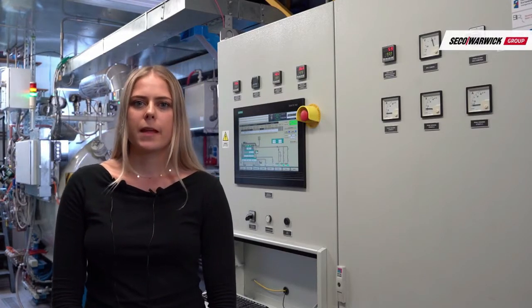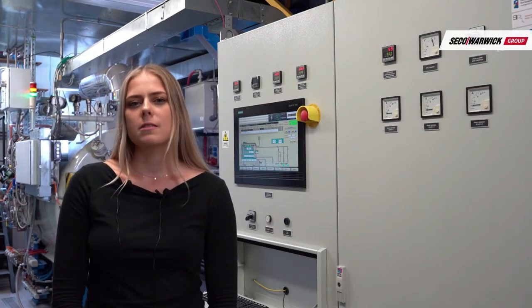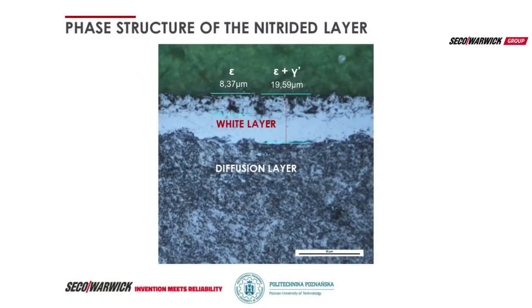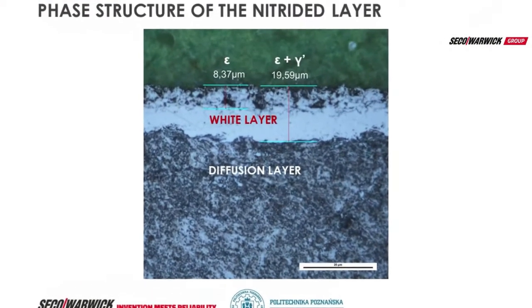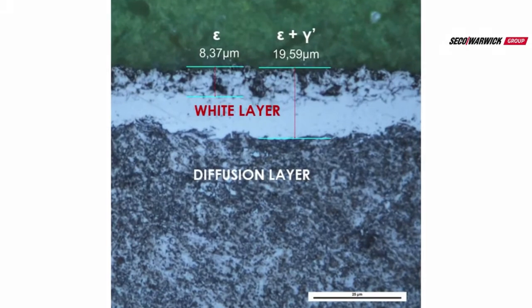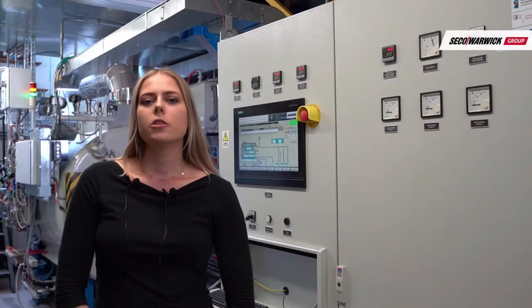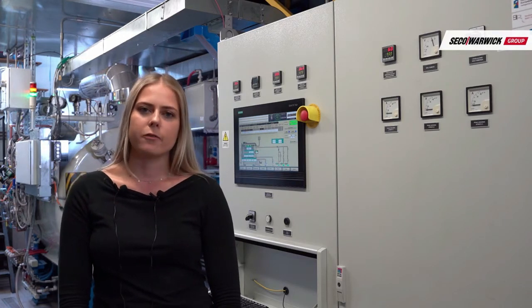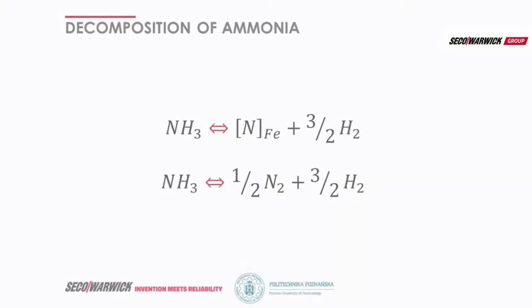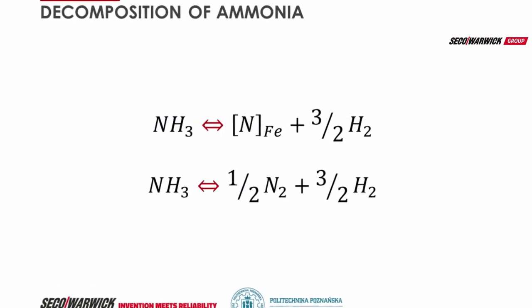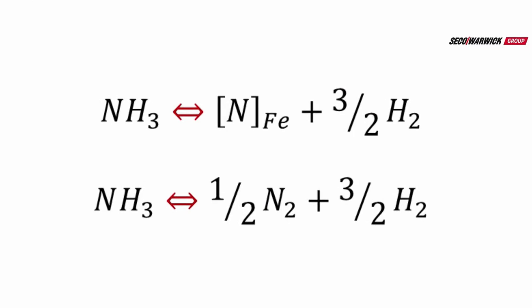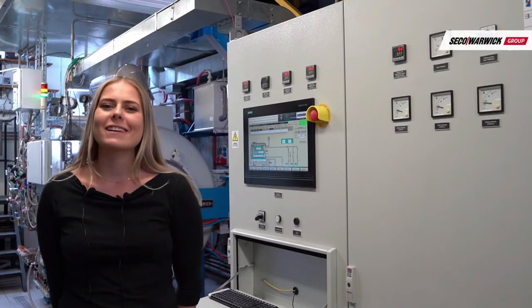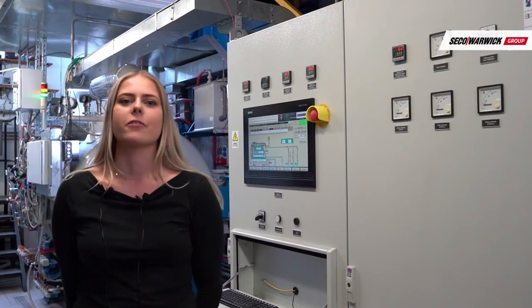The created diffusion layer, depending on nitriding potential, can consist of epsilon, gamma prime, alpha, and alpha phase. During nitriding processes at high temperatures, reaching between 490 and 560 degrees Celsius, ammonia, when in contact with metal surfaces, decomposes into nitrogen and hydrogen. As a result of those reactions, the atmosphere in the furnace consists of ammonia, hydrogen, and nitrogen.